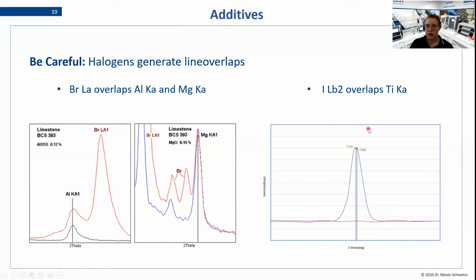Now we could say, okay, then let's just use some other halogen, for example, iodine. But the iodine L-beta 2 line overlaps with the titanium K alpha line. We can see it down here in this graphic. The red line displays a sample without any titanium and any iodine, and the blue line here shows the same sample not containing any titanium, but some iodine was added. And we can see here that it actually looks as if there is titanium, because the iodine L-beta 2 line is directly under the titanium K alpha line there. So be careful about that.